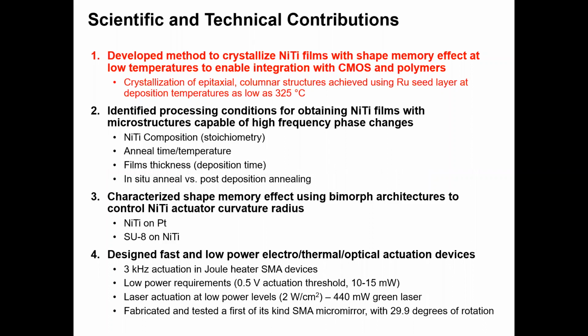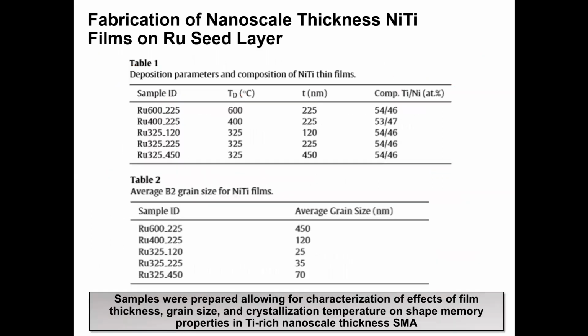So in this section, I'll describe the methods developed to crystallize nanoscale thickness NiTi films with shape memory effects at lowered processing temperatures. So table 1 here shows the deposition parameters used to sputter nanoscale thickness NiTi films for this study. A slightly titanium-rich composition was chosen, which has been correlated to lowered crystallization temperatures in some other works.